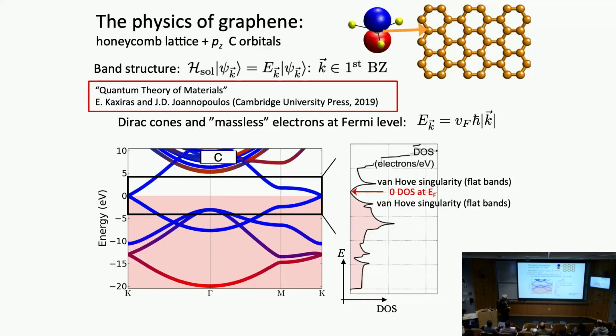Interestingly enough, the density of states at the Fermi level is exactly zero. There's no electronic states available at the Fermi level. But if you move a little bit away from the Fermi level, either positive or negative, you find states that you can occupy there. The region where you see very important, interesting behavior is when the density of states tends to have these kinds of divergences. So the density of states nearly diverges here. Those are called Van Hove singularities. And it was realized that if you could access these regions here, either on the hole side or on the electron side, you could have very exciting physics because nature doesn't like divergences. The system would respond by doing some interesting kind of behavior, and you would get all sorts of interesting correlated electron behaviors. So that had been hypothesized.